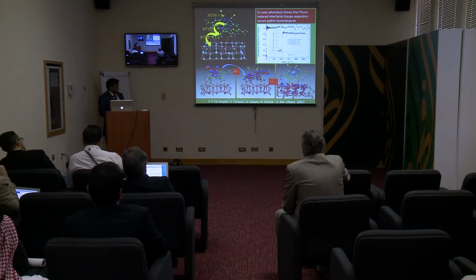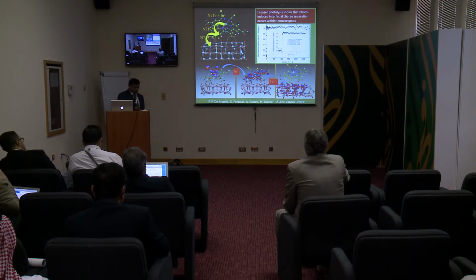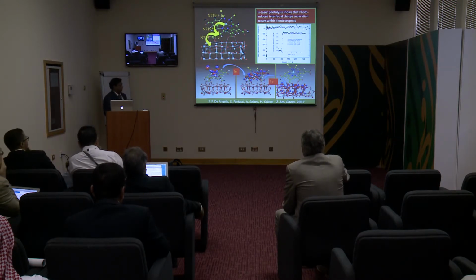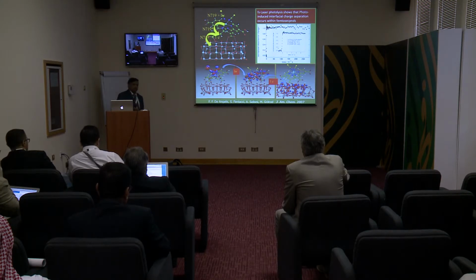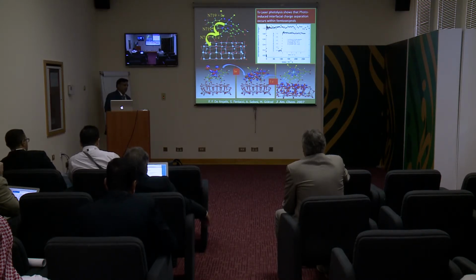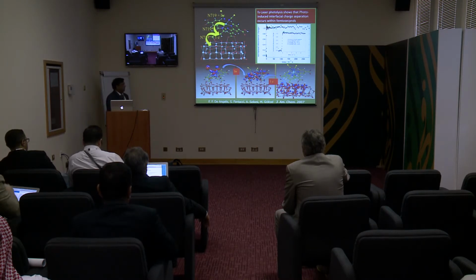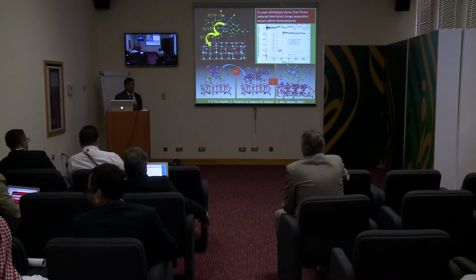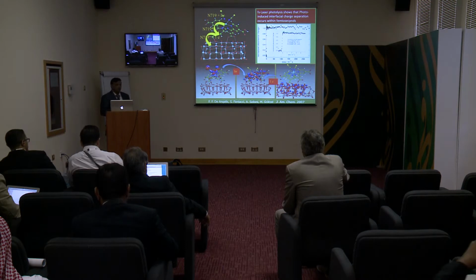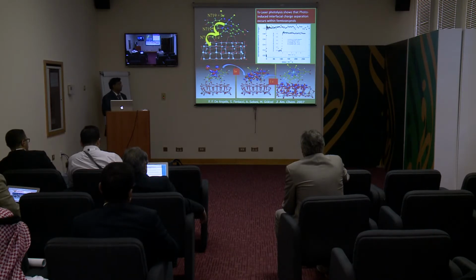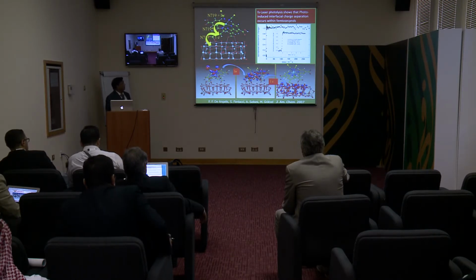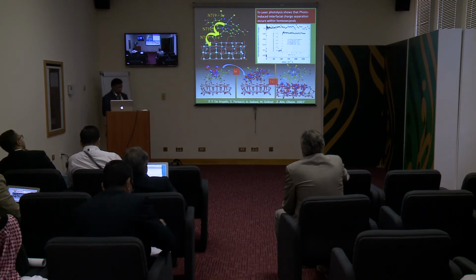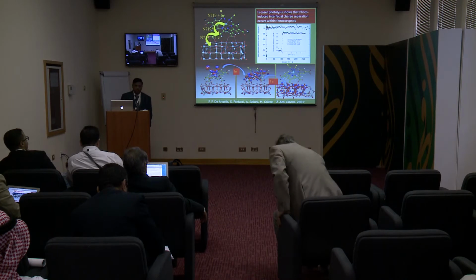For example, Filippo has worked on theoretical modeling to show how the dye is adsorbed on the TiO2 surface and how it binds and coordinates to the TiO2. If you take this N3 dye, where we have two bipyridine ligands with carboxyl groups, it has different possible modes of binding to the TiO2 surface. But the best optimized condition takes one carboxyl group from each ligand to bind to the surface, which gives you the lowest energy conformation.